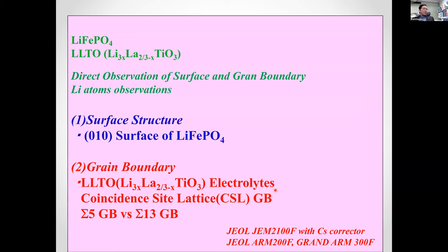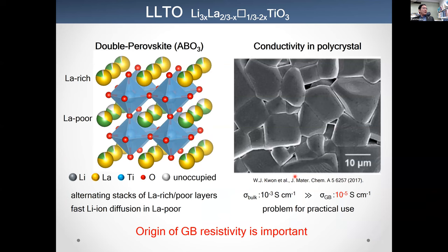LLTO electrolytes we used, and we characterize the grain boundary resistivity from the viewpoint of the grain boundary character. So this is LLTO, a double perovskite structure. It has a double perovskite structure, where lanthanum-rich layers and lanthanum-poor layers are alternately stacked along the C-axis. This is a polycrystal sample of the LLTO.